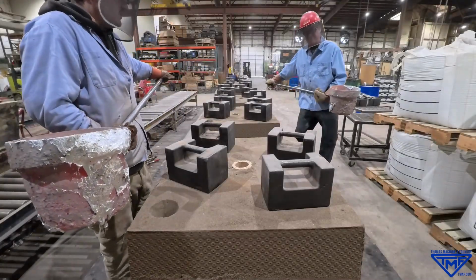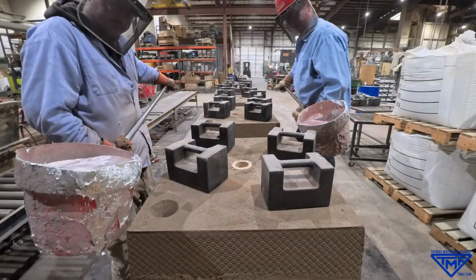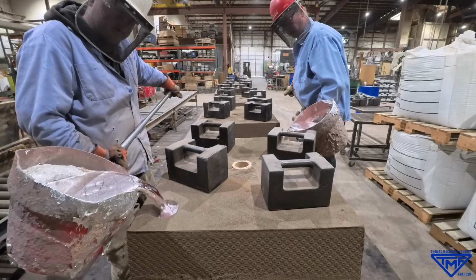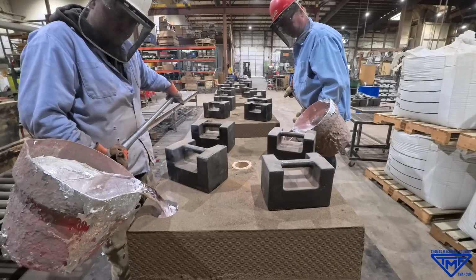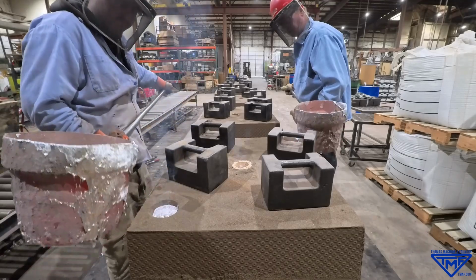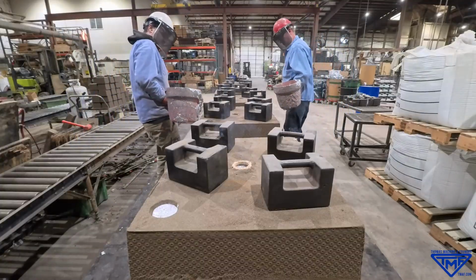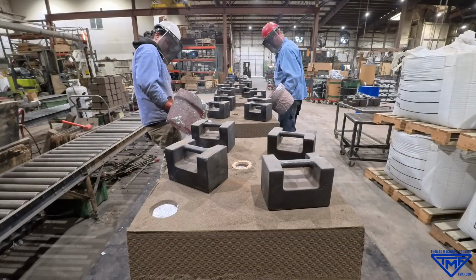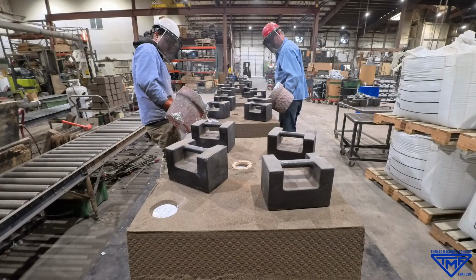Here, Jeffrey and Randy pour molten aluminum into the mold in unison. The metal flows through the sprue system and evenly throughout the part, eventually rising into the thermal riser. As the mold cools, the riser continues feeding molten metal into the casting below.